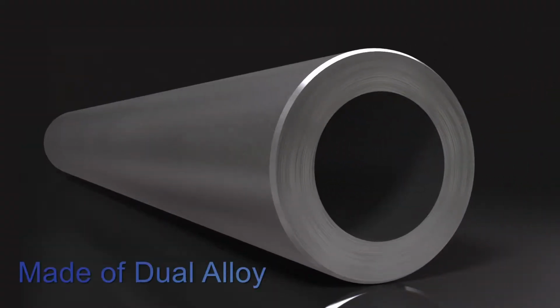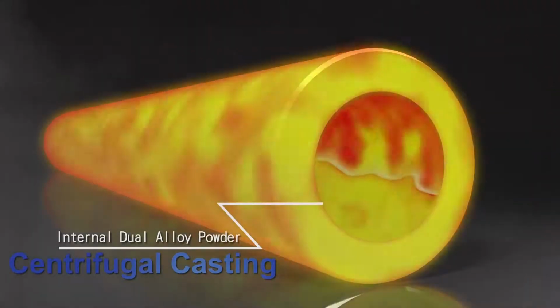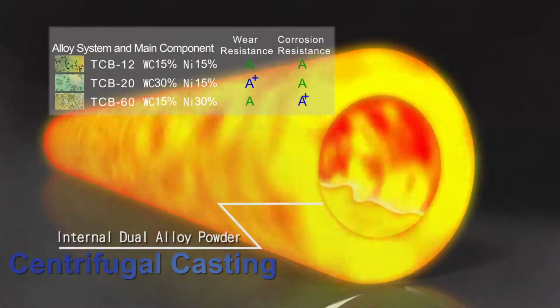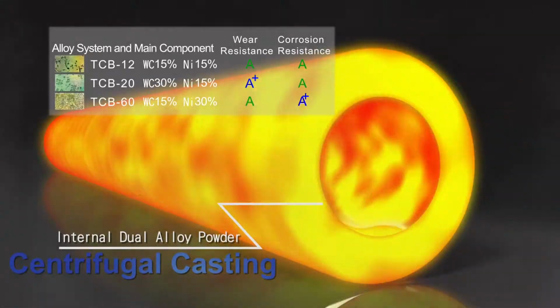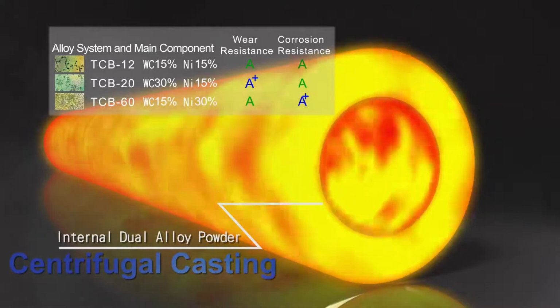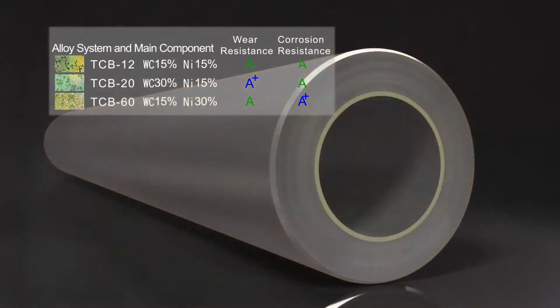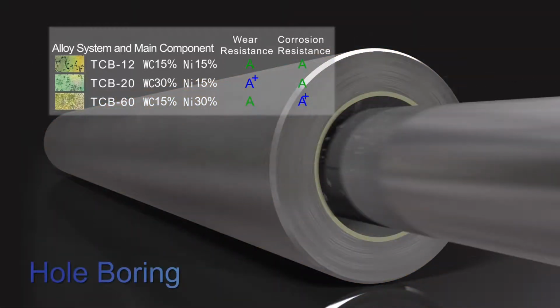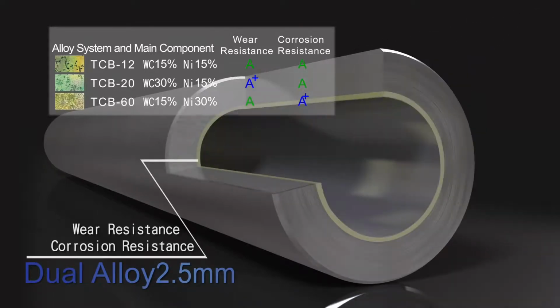Bimetallic barrels. To achieve barrel straightness and roundness, they are ground after going through centrifugal casting and rough boring. The thickness on a single side of the barrel is 2.5 millimeters. It has the properties of wear durability and corrosion durability, with longer service time than normal barrels.